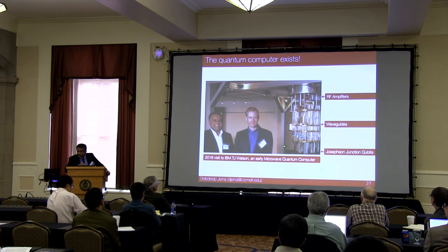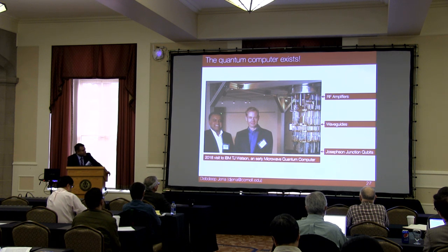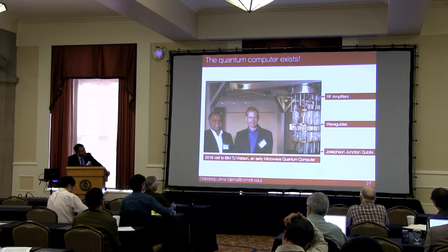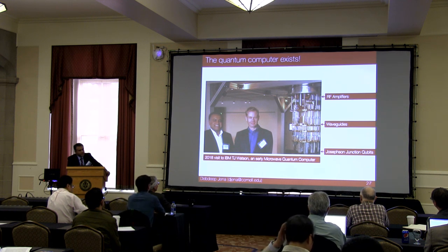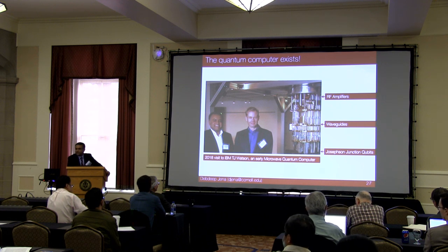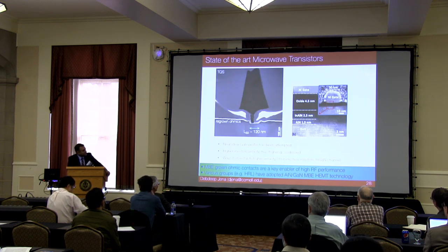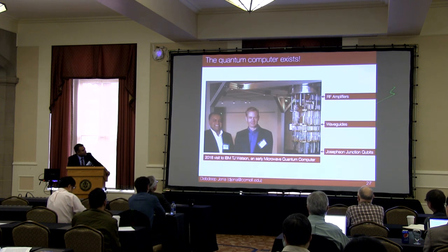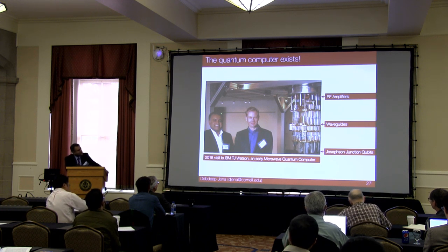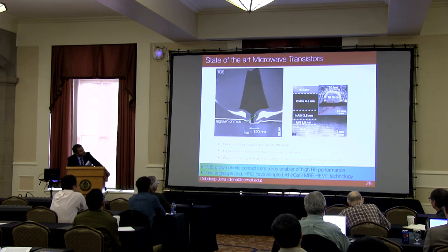Now, what is interesting is this transistor is fully functional. It switches, it has a large on-off ratio, and it has good current saturation, but it is also aware that it's sitting on top of a superconductor. If we measure the transistor carefully at a temperature above the superconducting critical temperature, it behaves like a normal transistor, with a metallic load, if you might, at the source end. But if you go below the critical temperature of the superconductor, you start seeing, already in the transistor characteristics, negative differential resistance. It's picking up the fact that it's sitting on a superconductor and that it can cause phase transitions in the superconductor itself. So it's sort of a hybrid of the two, a semiconductor and a superconductor.